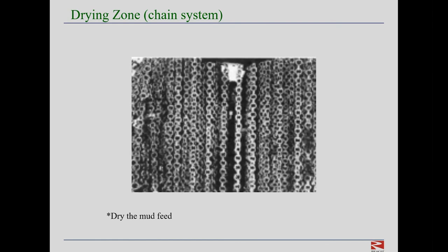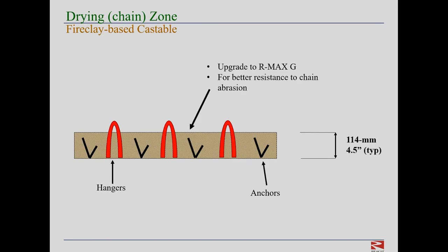Too little chain in the kiln results in mud that is not completely dry. The wet mud feed becomes sticky, leading to mud rings, which potentially leads to plugging the kiln. The cooler portion of a chain system is usually unlined. Historically, the refractory in the hotter portion of the chain system was a high-strength castable or gunning mix, held in place with metallic V-anchors, with chain hangers welded to the kiln shell prior to installation. Abrasion and impact from the chains can eventually cause refractory wear. In a retrofit or maintenance repair of a castable-lined chain system, RMAX-G or RMAX-G-QT should be considered for a longer-lasting lining.